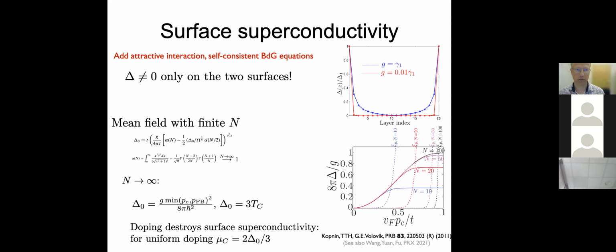So this is of course the normal state. Then you can consider what happens if you add an attractive interaction and solve, for example, the Bogoliubov-de Gennes equations to find the mean field order parameter and also its position dependence. What you find is that the order parameter peaks at the surfaces. So you have surface superconductivity, whose range depends on the ratio of the coupling strength and the hopping strength. You can then also study this mean field equation, what happens to delta with respect to the spectrum with a finite n.